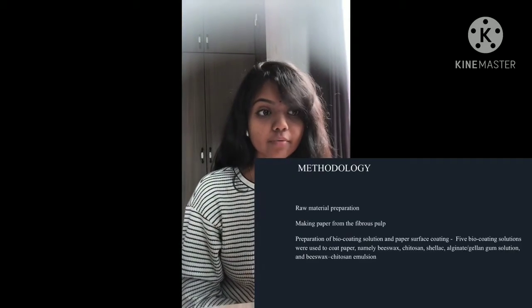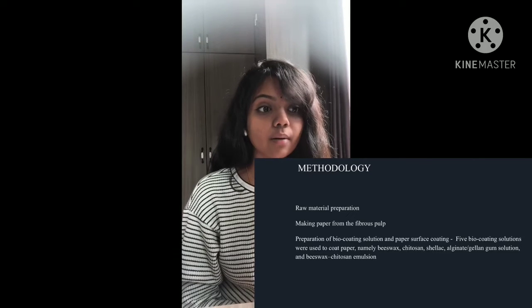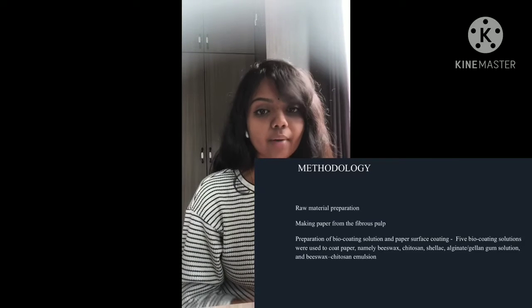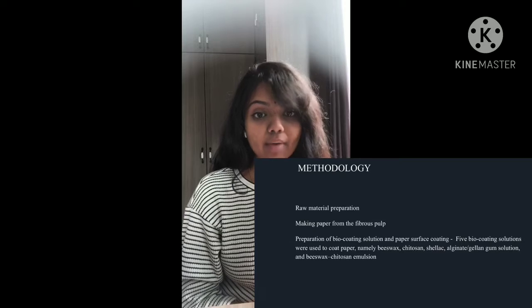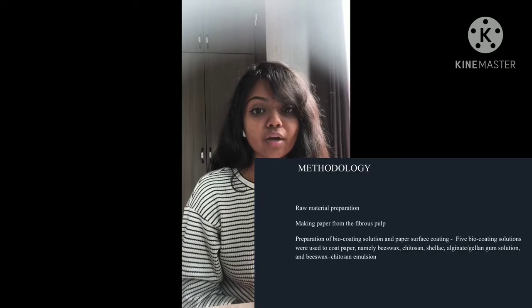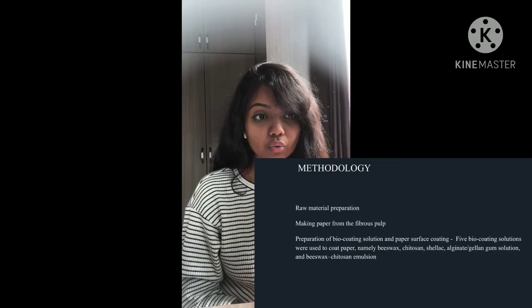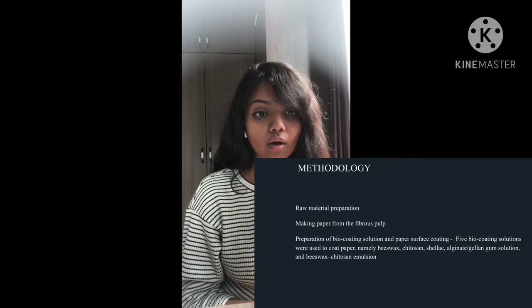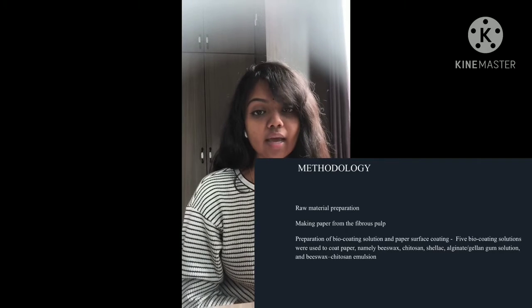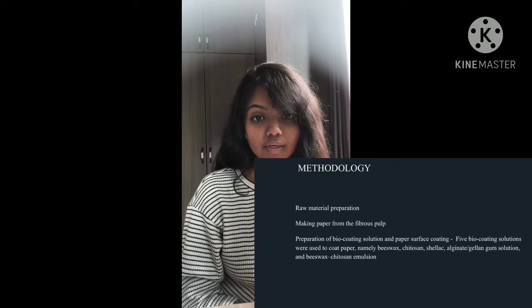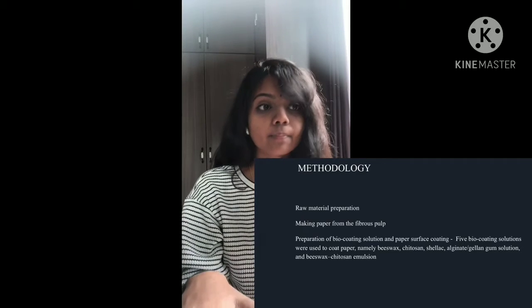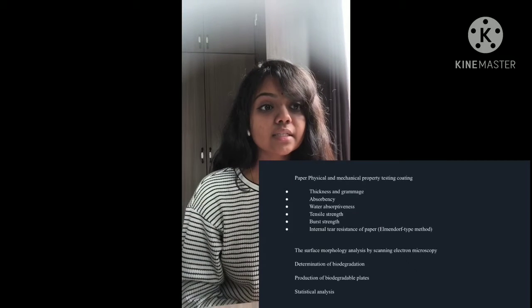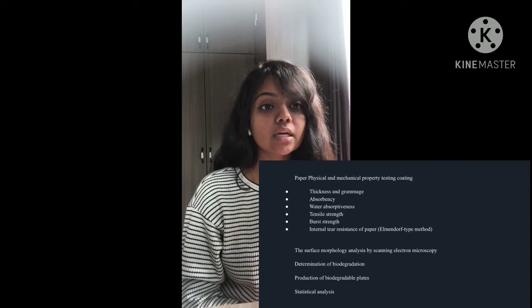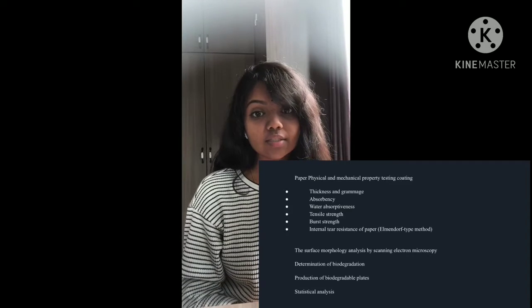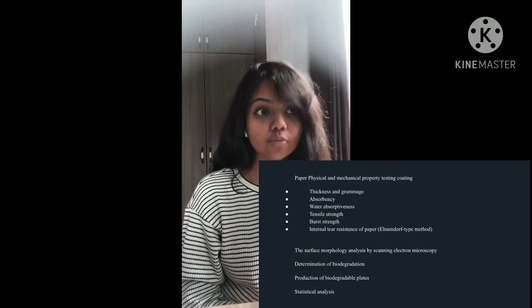So on the methodology, there was raw material preparation, making paper from the fibrous pulp, and the preparation of the biocoating solution and paper surface coating. There are 5 biocoating solutions that were used, which were beeswax chitosan, shellac, alginate, gellan gum solution, and beeswax chitosan emulsion. The paper physical and mechanical property testing that was done included the thickness and grammage,